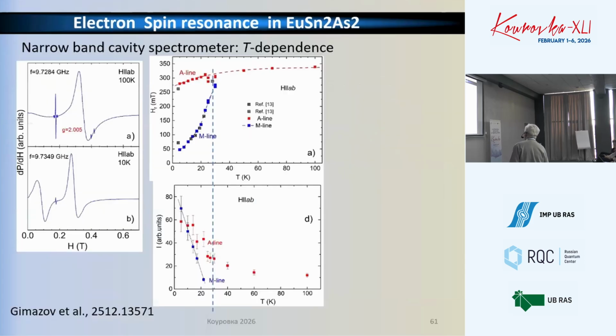So we use this fitting parameter and obtain quite reasonable fitting. Now we also did temperature dependence measurements using a cavity type spectrometer, which is more sensitive. Therefore, we were able to trace the resonance up to almost room temperature. And you see how the ferromagnetic resonance develops and merges here with the antiferromagnetic resonance, and further they go as a single paramagnetic resonance.